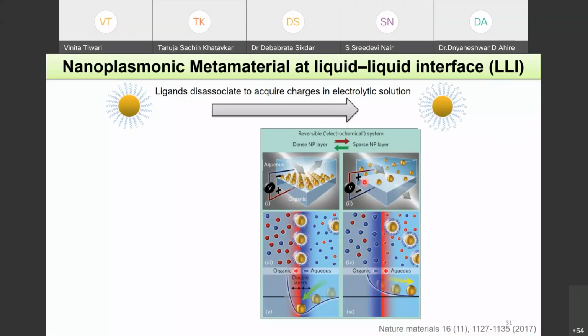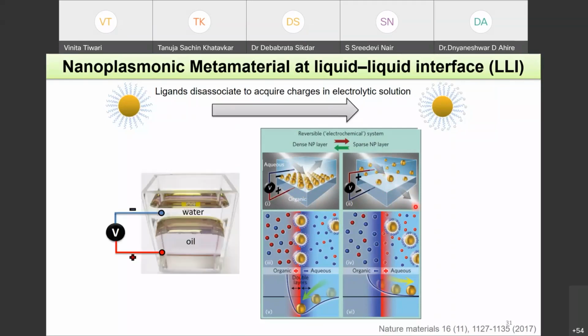But when you reverse the polarity, that is when you make the water phase positive, you actually attract all the nanoparticles towards the electrode. So all the nanoparticles will depopulate your interface and it will become transparent like a window. So this is one example of a mirror that is formed. So this is the reflection. This is the actual mirror that is formed at the water-oil interface by the nanoparticles. You can see how good a mirror this is. And if you apply the potential, you can actually construct or destruct the mirror.